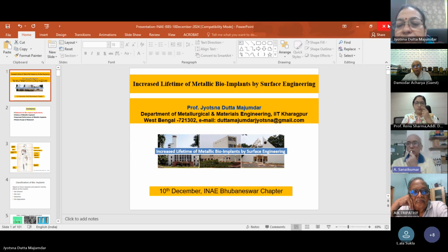Number two is that we find that wear resistance is much better if the hardness of the base material is very high. You are using 316L, which in our opinion is not a very hard material. Stainless steel 316L is fairly soft. We use a precipitation hardening material, 17-4 PH stainless steel. It can be heat treated to as much as Rockwell 32C. On top of that we chromium plate or we nitride. Nitriding also, as you said, produces chromium nitrides. That's correct, the same thing happens.